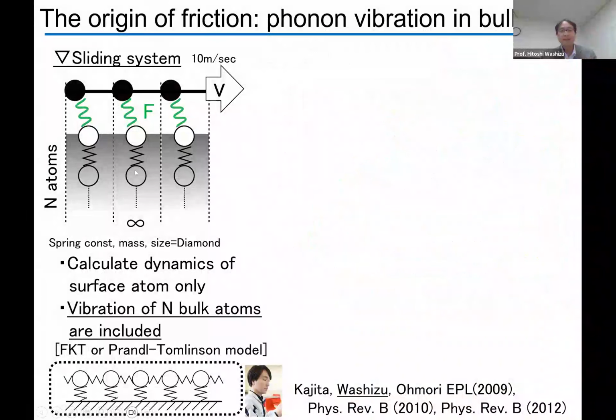But in a realistic situation, well, I'm half a physicist and half a chemist, so I'd like to use a much more realistic system. In this case, we added a number of atoms in the bulk side, okay? And then we calculated the friction. So what happened? We used parameters for diamond, spring constant, and mass. 10 meters per second is a little bit slow from the molecular point of view. But I once worked in the automotive industry, and this is a realistic speed for a combustion engine. We put in these parameters and then calculated this.